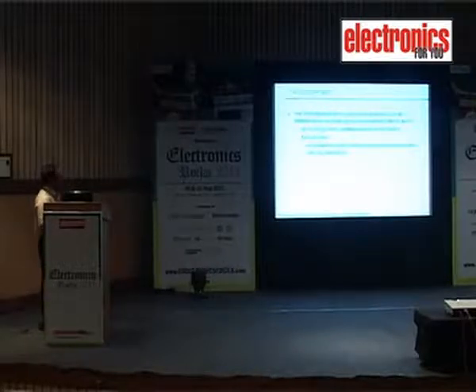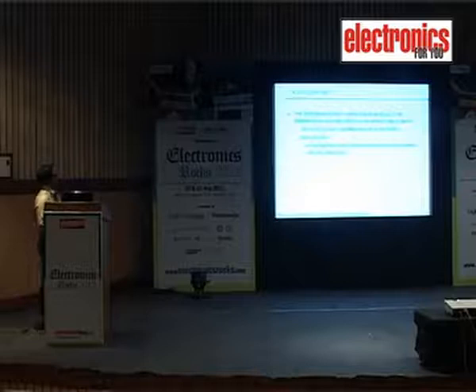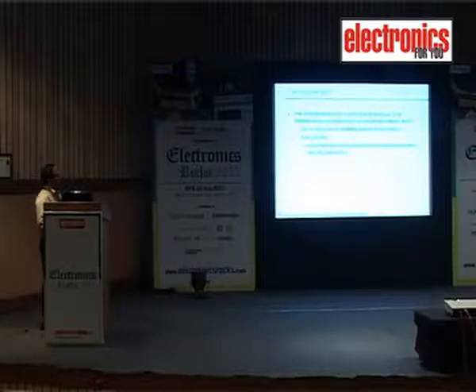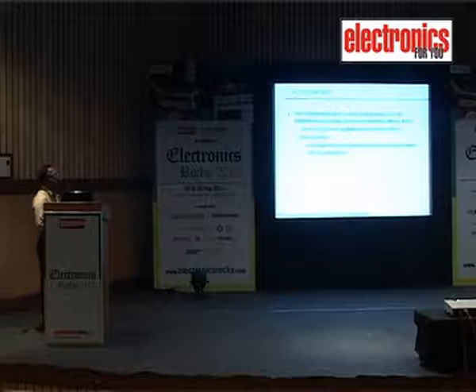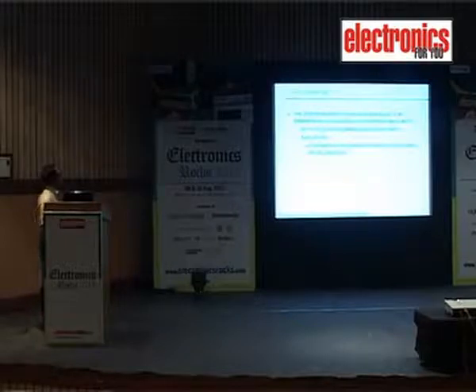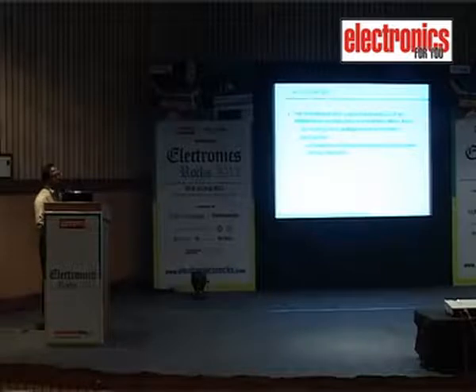That is measling. Then blistering is one of the enemies of the PCB, where you find a bulging, that means delamination. It takes delamination at the surface of the PCBs, causing traces to come out of the PCB itself. Such a thing should never happen. So to verify whether the PCB is able to take up all those things, we do hot oil dip test at 260 degrees centigrade.